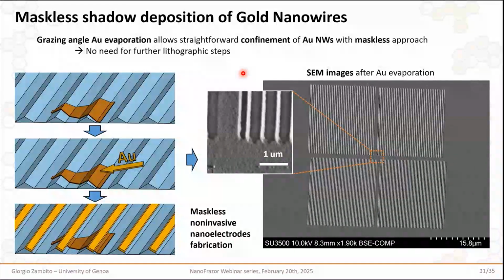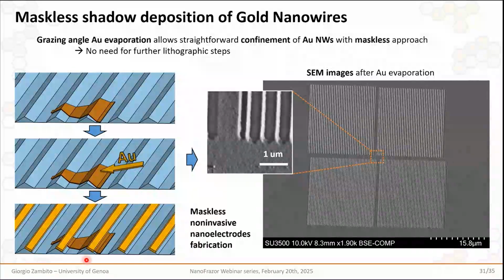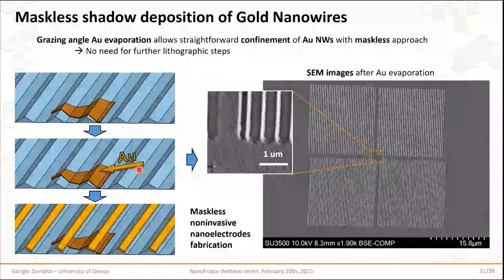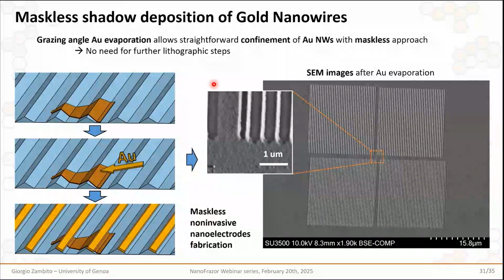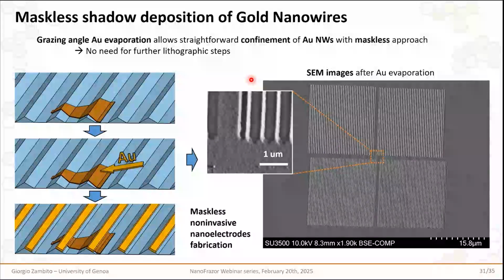And this is achieved via grazing angle gold evaporation, which allows us to confine gold in the form of nanowires thanks to the shadowing effect that is formed between one ridge and the other when you give a flux of gold with a certain inclination, in this case 10 degrees with respect to the surface. This is observed on bare faceted PPA, for example, from these SEM images after gold evaporation, where these bright lines represent the confinement of gold, and these dark regions represent bare exposed PPA that has been protected by this shadowing effect.